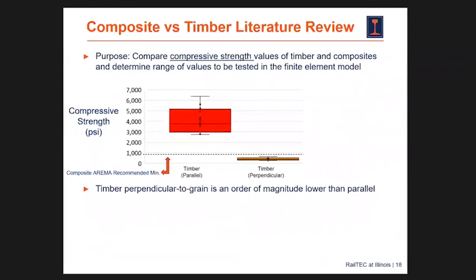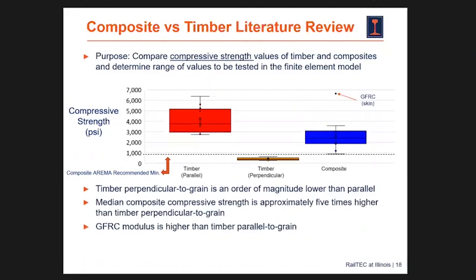But if we go to compressive strength instead of modulus of elasticity, compressive strength, again, about an order of magnitude lower perpendicular. That's why we crush the timber all the time. But now these composite ties, even the median value is about 5 times higher than timber perpendicular. So this is something we can start working with. We might not be crushing any sort of composite material that's out there. And this GFRC is substantially higher even than the timber parallel to grain. So now this is something that could provide a very good benefit to reducing the amount of crushing. And so this again gives us a range of values that we can play around with in the model.